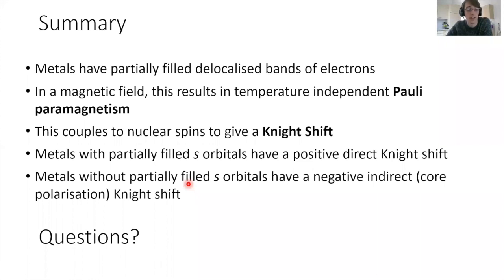What dictates the magnitude is how close that valence orbital gets to the core s orbitals, so how much density there is nearby. And something I didn't get into is that for 2p orbitals, the indirect Knight shift is actually positive because it polarizes your core orbital the other direction. So you have to be a little careful with elements that are early on in the periodic table because you can get unexpected results there. But yes, in general, they apply to all non-s orbitals.